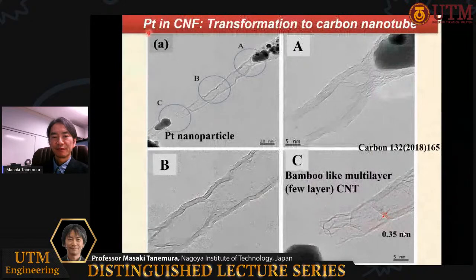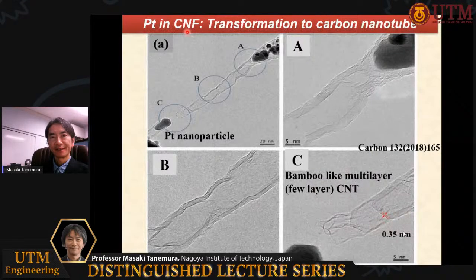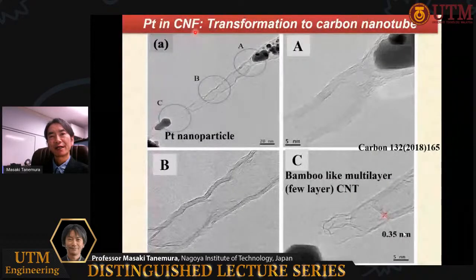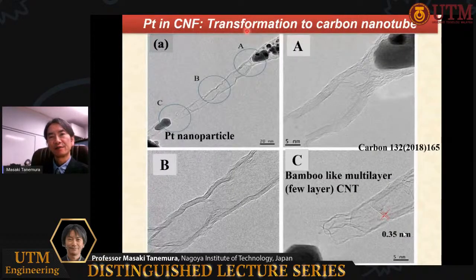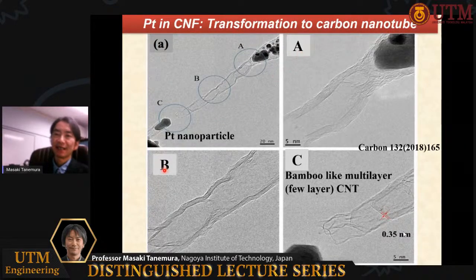This is a TEM image of the platinum nanoparticle case. For platinum nanoparticle, after the movement of platinum, transformation from amorphous to carbon nanotube occurs. Images A, B, C are the enlarged images of those A, B, C, respectively. Here is a carbon nanotube formed after the movement of platinum nanoparticles. Here you see platinum nanoparticle, and here is a broken part.